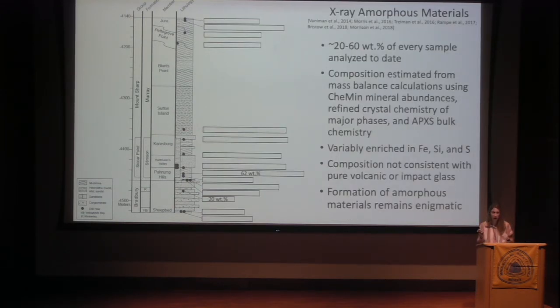Okay, I'm pretty sure I don't have a lot of time to talk about the X-ray amorphous materials, but I just want to mention them. It was a complete surprise that every sample that we have analyzed to date, not just these ancient fluvial lacustrine samples, but also the ancient aeolian samples and the modern aeolian samples, have abundant X-ray amorphous materials, 20 to 60 weight percent of every sample. We can constrain the composition of this X-ray amorphous component using the crystal chemistry from CheMin and the bulk chemistry from APXS.